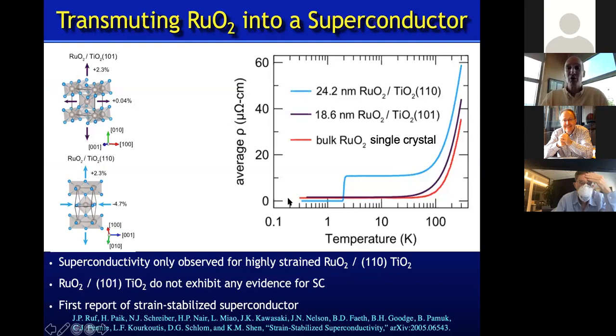Okay, so here I'm showing you control samples as well as a bulk single crystal of ruthenium oxide. They're nice metals to very low temperatures. But what we found is that if we put the ruthenium oxide on titanium oxide, so it's a rutile, here's the crystal structure. These are top views of the films that we've made on two different orientations of titanium oxide, rutile, substrate. So perovskites grow well on perovskites, rutiles grow well on rutiles. TiO2 is the only commercial rutile oxide substrate.